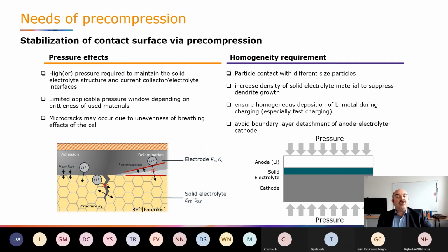The pressure has to be applied also very homogeneously to enable particle contact with different size particles and homogeneous deposition of lithium metal during the fast charging process. This pressure also avoids dendrite growth or boundary layer detachment.